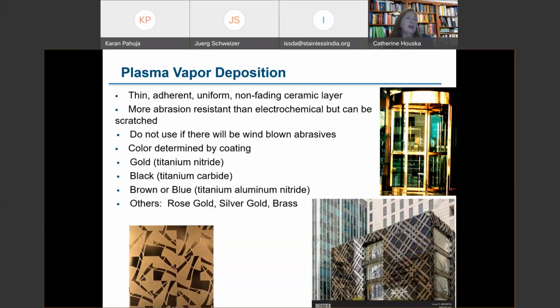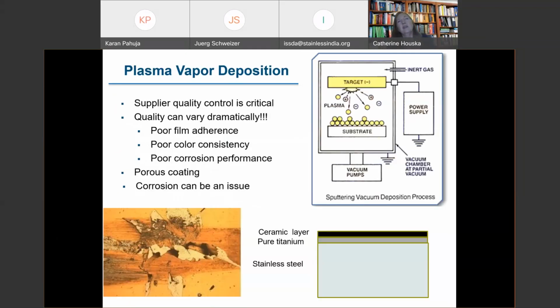The bottom left shows this finish applied over an etched surface. So you can see that the etching is still visible. The Burberry store in Chicago is the bottom right, and there's both black and gold bands with this finish. So this is applied by placing a clean stainless steel panel in a vacuum chamber.